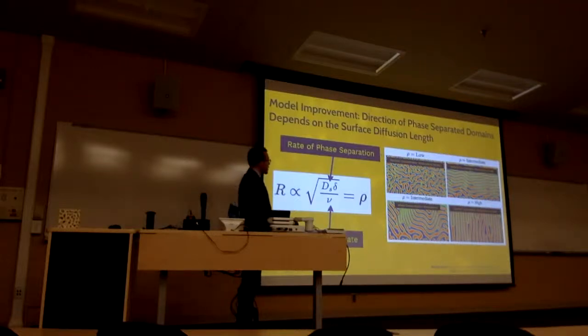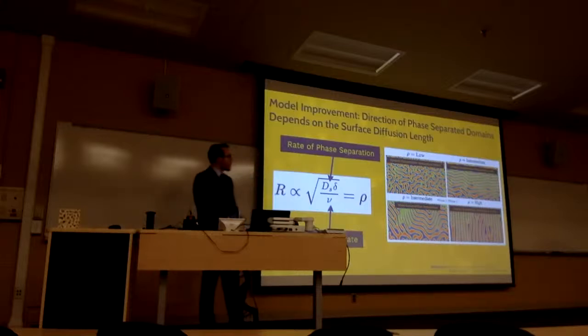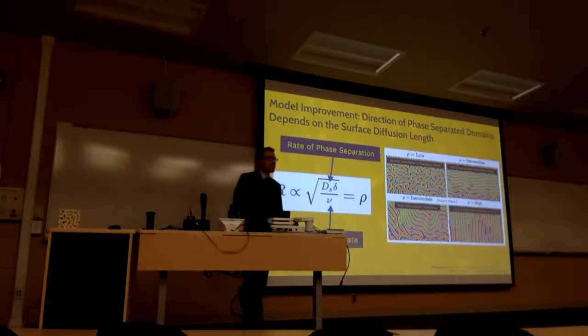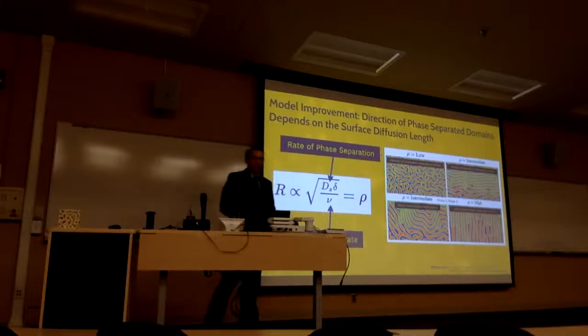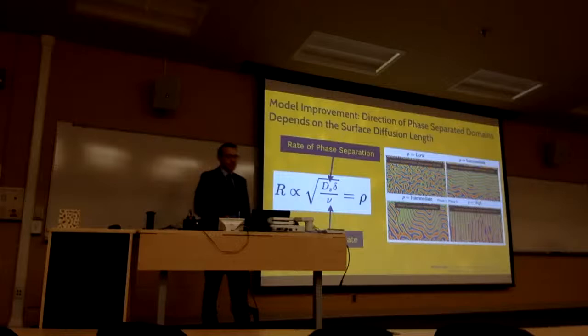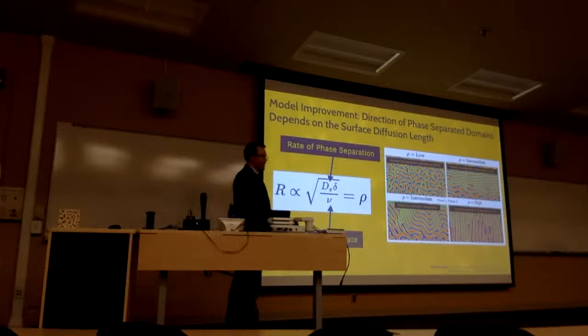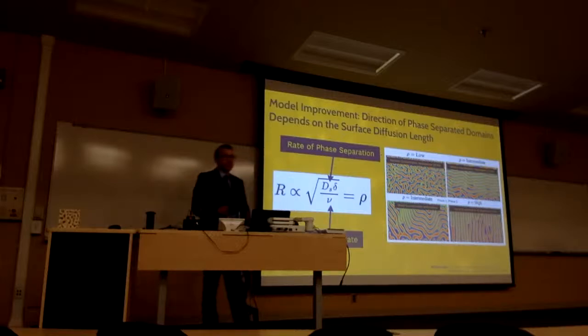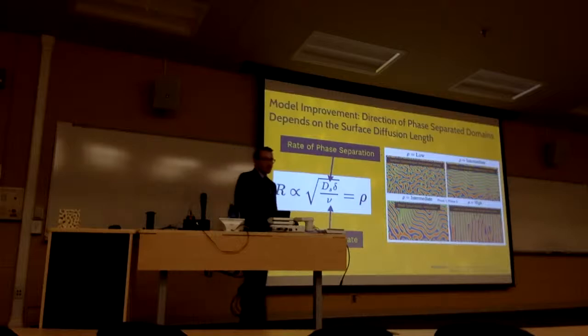And you can see that as a function of rho, this surface diffusion length, we can change the morphology or the direction of concentration modulations in the sample. So you can see these red and blue phases, this is a two-phase material. You can see at high surface diffusion length, we have this lateral concentration modulation. And as this rho value changes, we see the randomization of this morphology as a function of the deposition conditions.